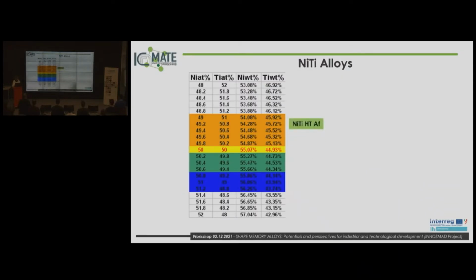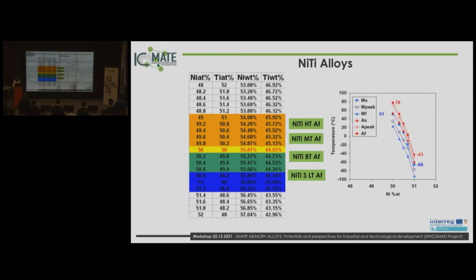When we have to choose the nickel-titanium alloy, we have to choose the temperature range for the application, and then we consider the particular composition of the nickel-titanium. This system is very open, because by changing the chemical composition, starting from, for example, the atomic composition of nickel 49 to 51.2, we can move the temperature by about 100 degrees. Then the control of the chemical composition, the control of the microstructure, of the preparation of the nickel-titanium alloys is very, very important to develop the application.